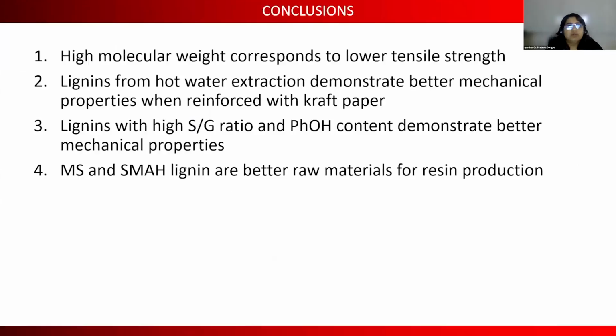So overall, my conclusions are that higher molecular weight of the resin corresponded to lower tensile strength because of extensive cross-linking. Lignins from the hot water extracted process demonstrate good mechanical properties, sometimes even better mechanical properties when reinforced with kraft paper or even with glass fiber studies. And the SG ratio and PHOH content are significant in determining how your resin would perform.